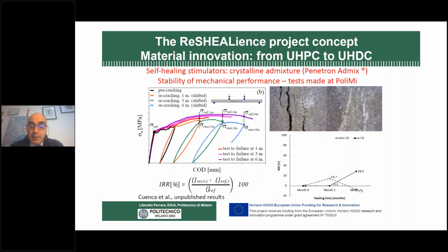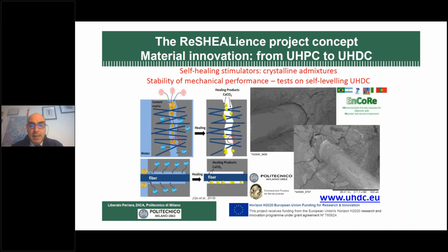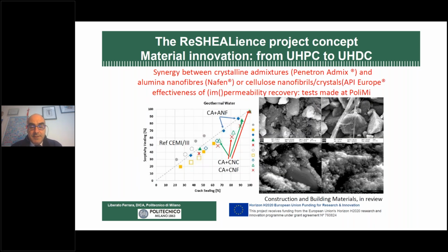We also checked, because we wanted to explicitly exploit this in the design, what self-healing means in terms of the ability of the material to maintain the mechanical properties over a long time, with repeated cycles of cracking and healing, which is what the structure will experience. And we also went into microscopic investigation to check the efficiency of the healing on the fiber matrix bond, as you can see from these graphs. And these are some images of the effects of the nanomaterials, the nano-alumina and the nano-cellulose.